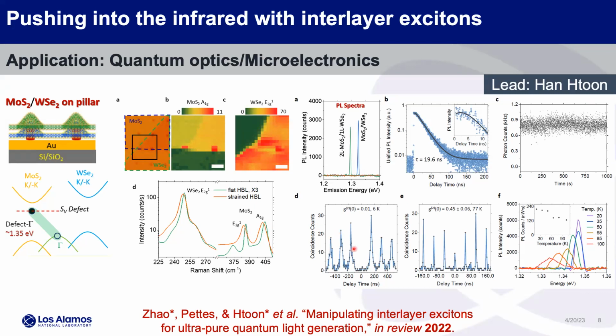But interestingly for us, G2 is even better because the lifetime's longer. So those single photons don't have a chance to diffuse and to recombine. So the ability to keep the defect isolated from the host is much better in this system. And then temperature dependence, it's not great, but we get results near 77 Kelvin that are still below the 0.5 G2. With our early work, we could never get anything to work above 5 Kelvin. Above 5 Kelvin, you don't see anything. So we're pretty happy. We're pushing the temperature up.